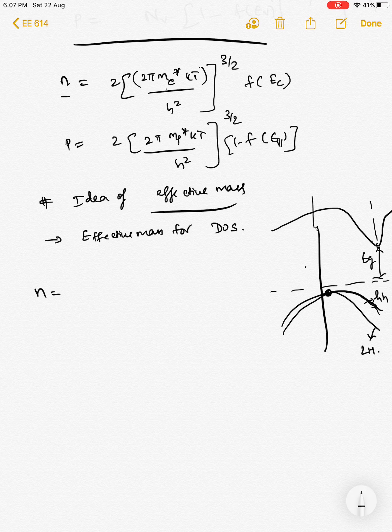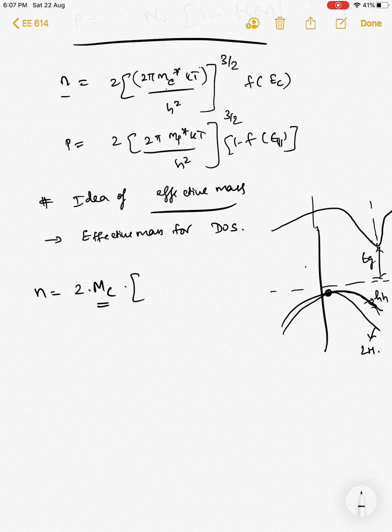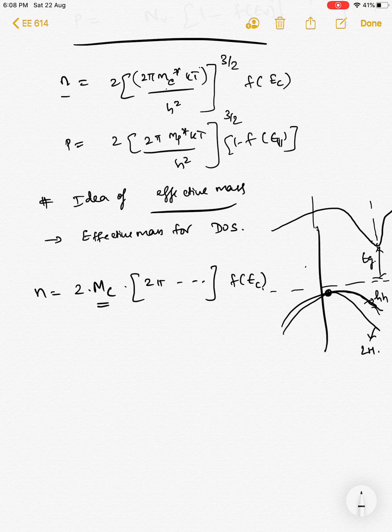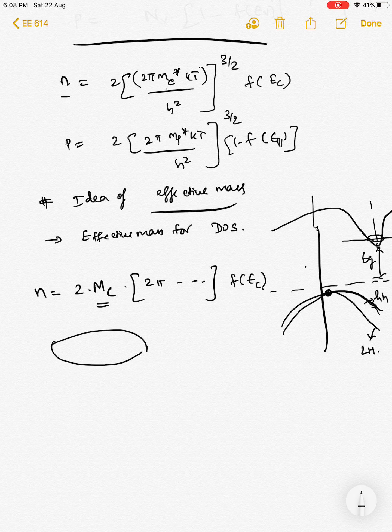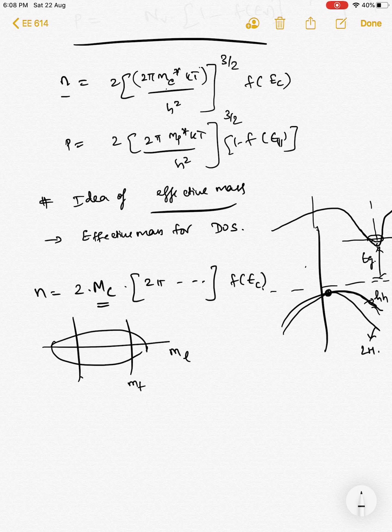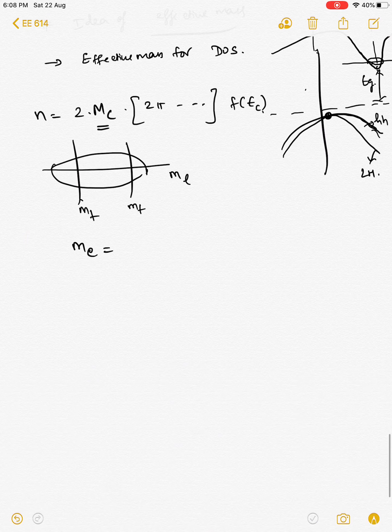So N_C, whatever we have defined, should actually be 2 times M_C — where M_C is the equivalent number of bands — times the standard expression (2π…)^(3/2) · f(E_C). In addition, we used m_e, the effective mass, which is the slope of the slope of this E-k curve. For silicon, the equi-energy surface is an ellipsoid, which has two different masses: a longitudinal effective mass and a transverse effective mass. The effective mass for the conduction band is then a geometric mean of these.